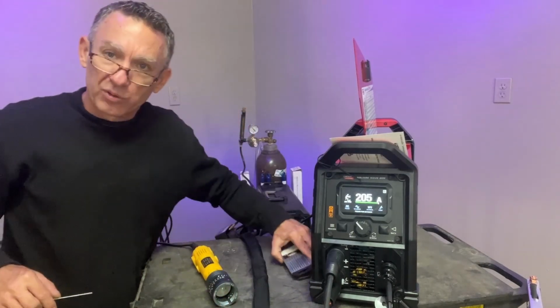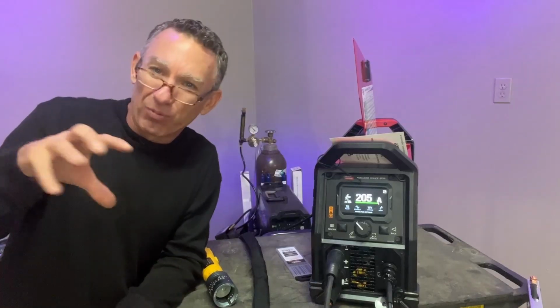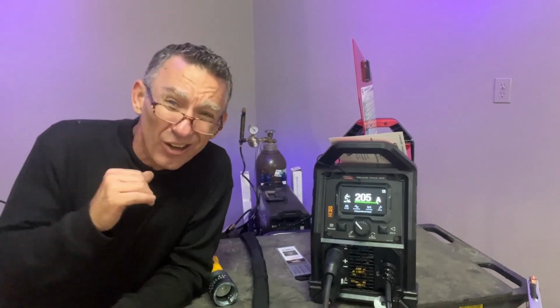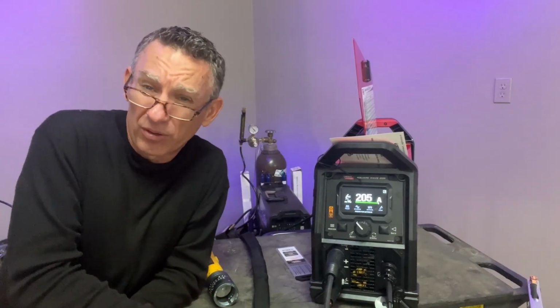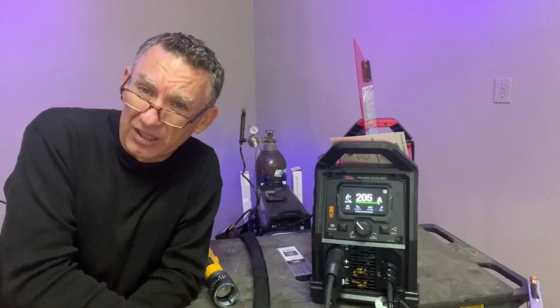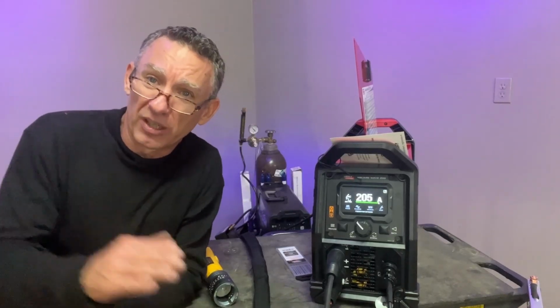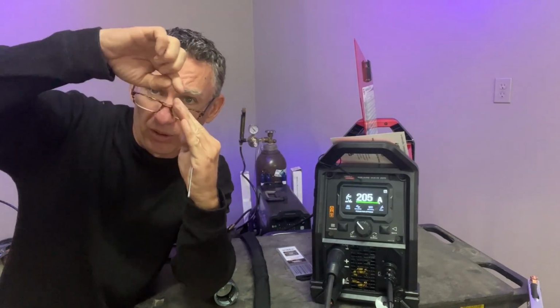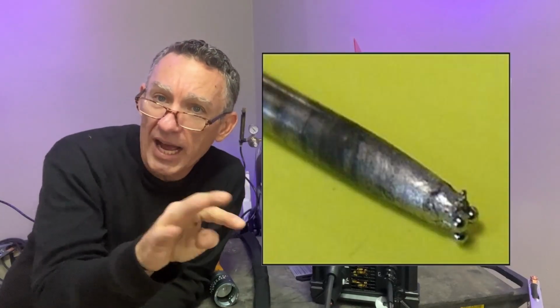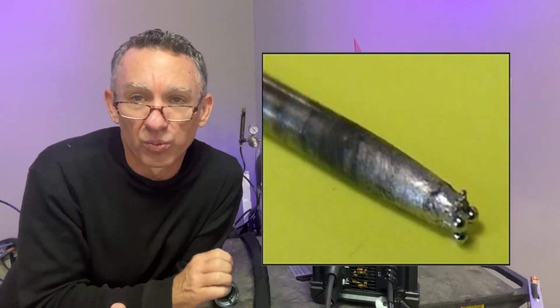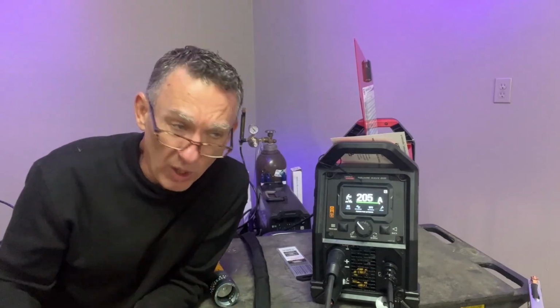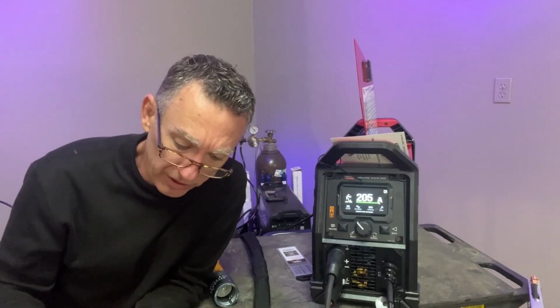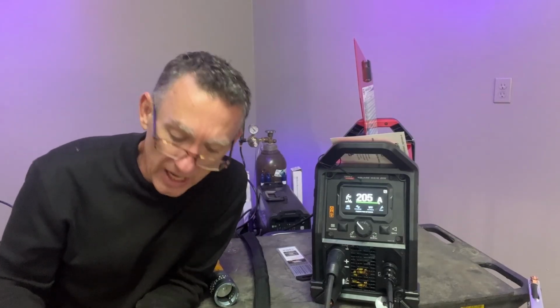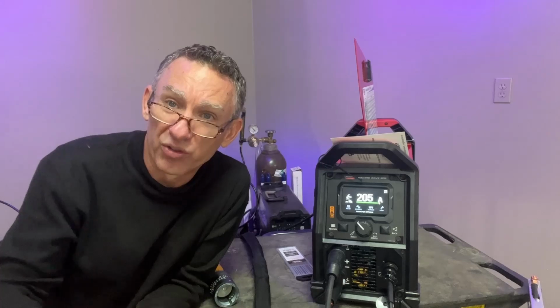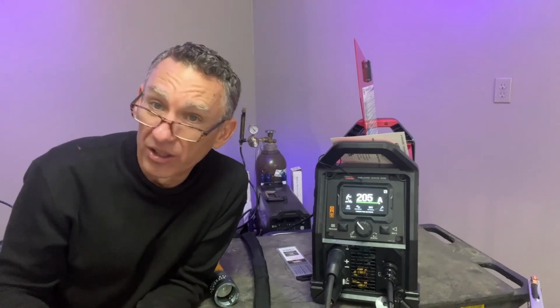When you use a thorium tungsten on AC, it tends to have really, really bad migration issues. Thorium does not like to ball, right? The thorium really resists it a ton, and what you'll get is instead of having a nice smooth tip with a little ball on the end, you'll have little nodules all over it that'll form, and that can cause really severe, ugly arc starts. Right in the late 90s, we started playing around with different electrodes, different settings, and I found out that cerium was outperforming thorium, you name it, right?